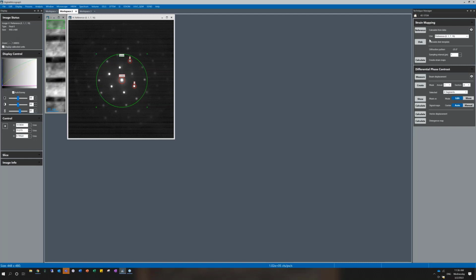Oh, one more thing to mention here, you can see we have a drop-down option for a reference diffraction image to use. This drop-down allows you to use a different diffraction image as a reference, something that has been calculated from a different data set, but a data set that has been collected with the exact same acquisition parameters. So you want the same convergence angle, the same camera length, the same camera parameters, but in a lot of cases, in a region of the sample where you are trying to calculate the strain, you do not have access to an unstrained area. So this is the solution for that.